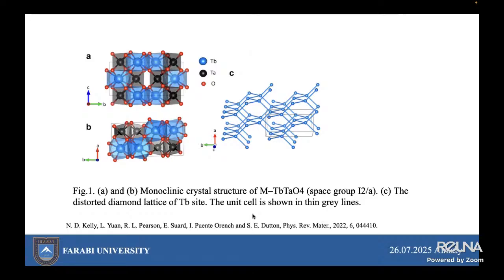Our variable temperature and field magnetic susceptibility and specific heat measurements allow us to track changes in the magnetism. And from these measurements, the Néel temperature is found to be suppressed by the magnetic field, and the transition to a different antiferromagnetic state is observed by applying the field.